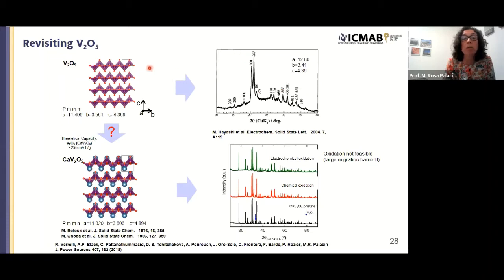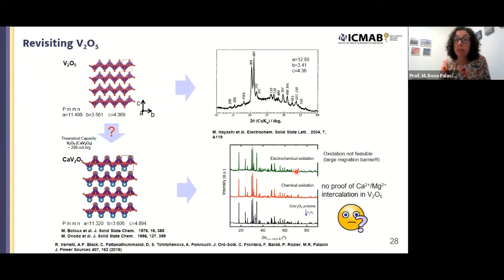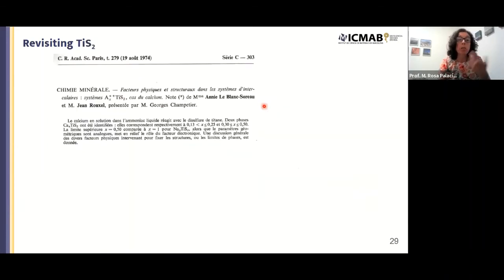And this is similar to some vanadium bronzes. And then we decided to do the opposite. Let's prepare this compound and let's try to extract calcium from the crystal structure. And again, this was not possible, neither electrochemically nor chemically. And the same was true for magnesium. So the message here is really that impurities in the electrolyte can make your life very complicated because protons are very mobile. So then finally, we also studied TiS2.